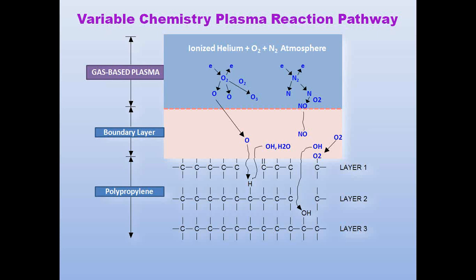And so if we're working with the adhesion of a solvent-based paint, of course, there's an opportunity to change the gas chemistries to allow us to functionalize that surface and create covalent bonding with that solvent carrier. If we're working with a UV-based light curable type of an adherent, that could be, again, an adhesive or a coating or an ink or paint, we would want more amine functionality. And of course, that would be part of the equation that would be introduced.